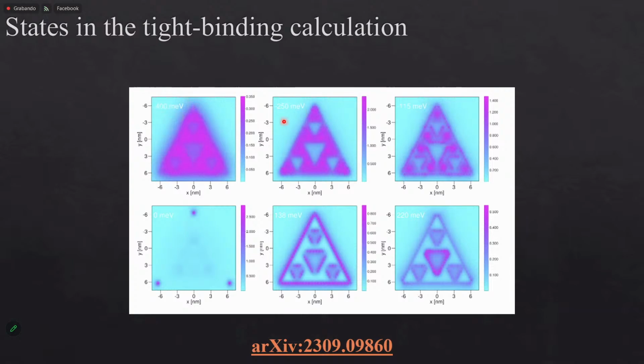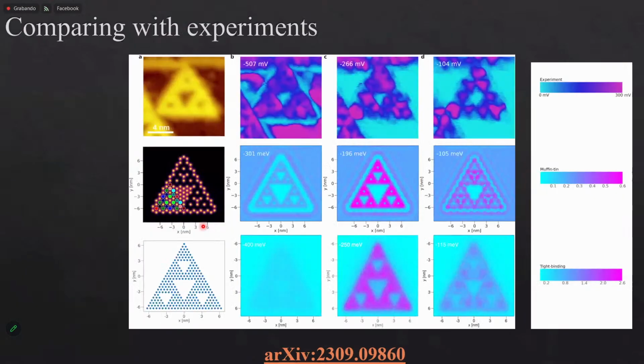We see that we have bulk states that have different symmetry, but they are bulk states. At the Fermi level, we have the corner states. And then we have edge states that can be either on all edges or just on the main edge. So you notice that the results are a bit different from the muffin-tin results, but we have the important feature that the system is an insulator in the bulk, but has states in the corner at the Fermi level. So now we can see whether this describes the experiments that they have.